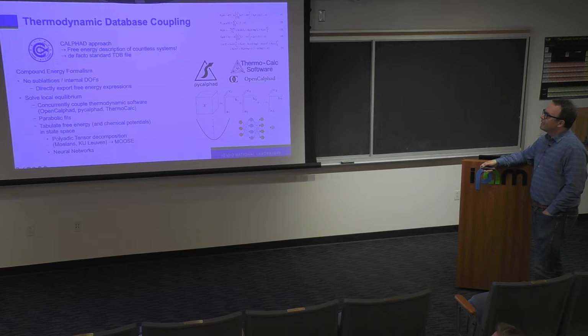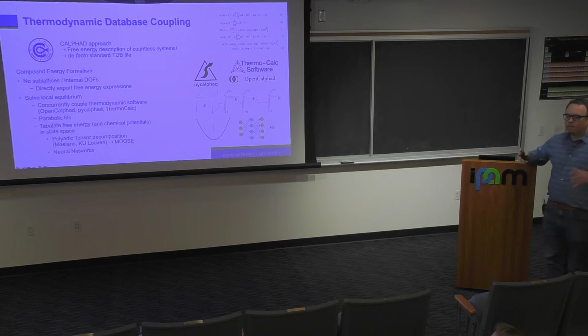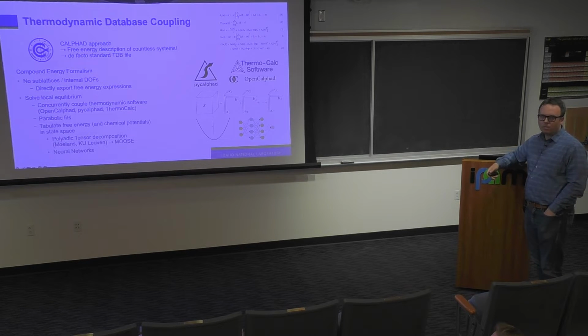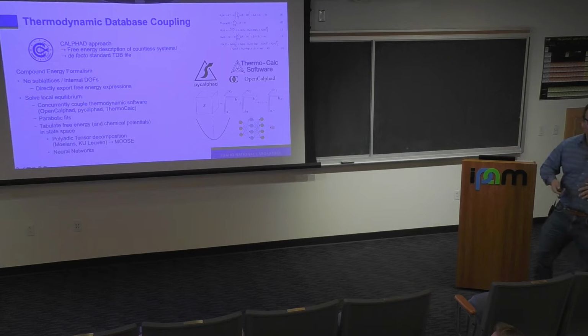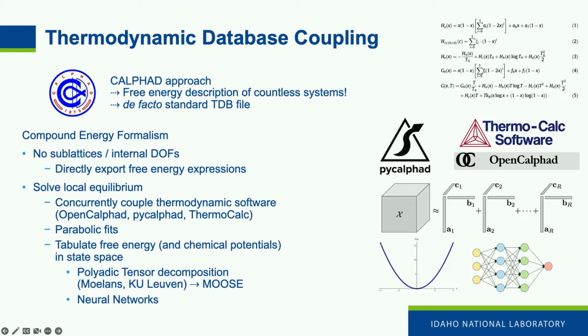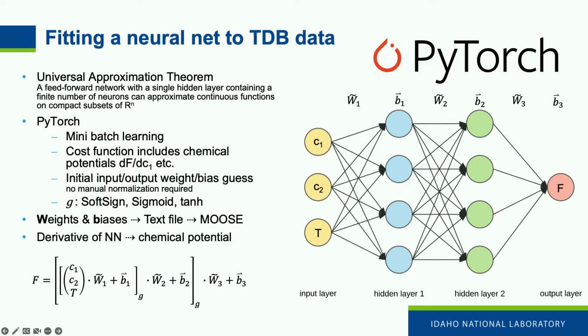Or if you have an open database, and in the nuclear community, there are databases like TAF-ID, for example, which have thermodynamic potentials for nuclear systems, uranium, zirconium. We have databases for molten salts, etc. We can get those equations out that describe the free energy surfaces, but we had a problem with the compound energy formalism, where a phase can have multiple sublattices with separate concentrations, and I'll talk about that in a second.